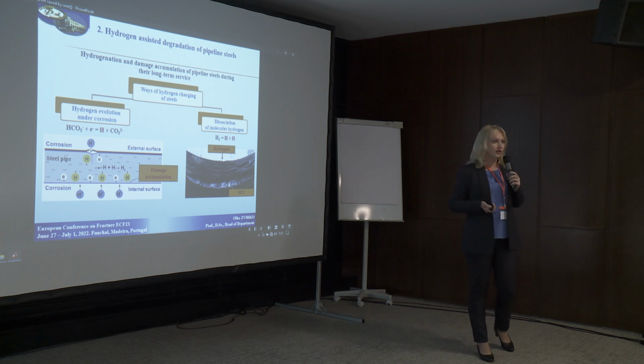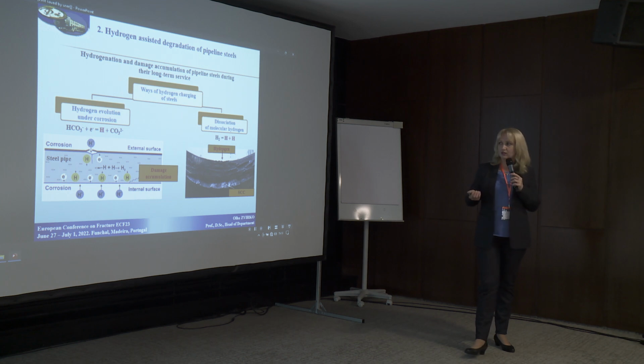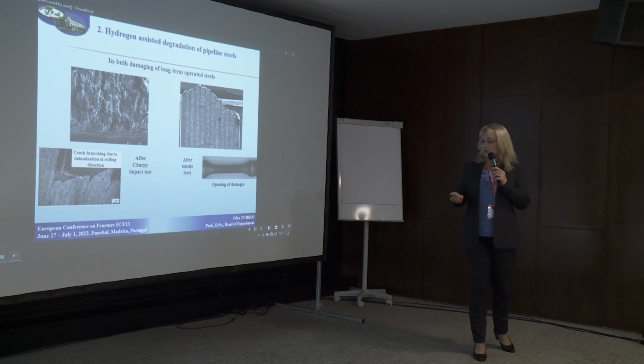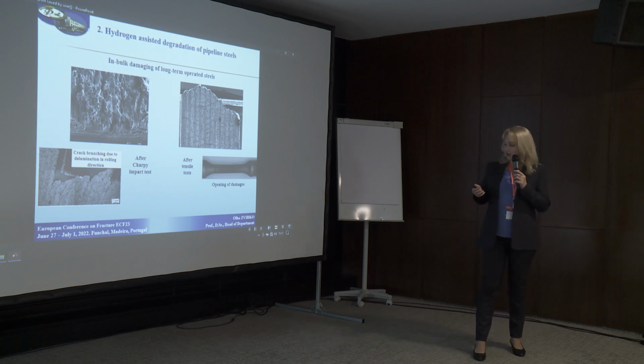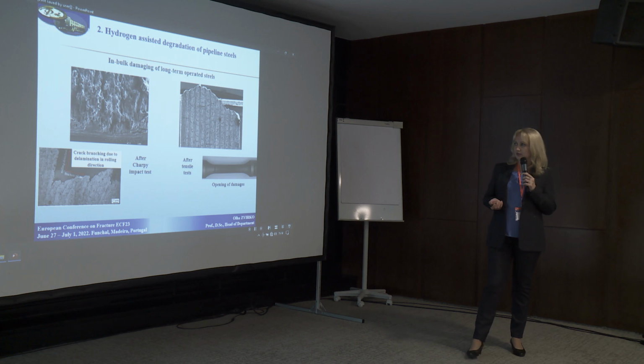So hydrogen, on the one hand, accelerates in-service degradation of steels and facilitates formation of damages, and on the other hand, it facilitates initiation and propagation of cracks in the damaged steel. Here you can see some examples of revealing of damage accumulation in pipeline steels by mechanical loading. It's also visible crack branching due to delamination in pipeline steel under impact testing, and also opening of damages under tensile testing.